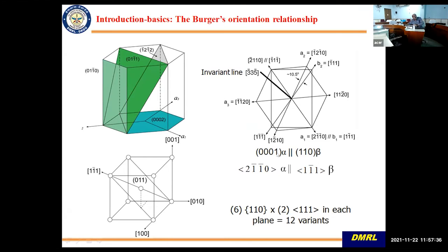So what happens is 001 of alpha, which is this basal plane, or 002 matches onto the 110 of beta, and one of the close pack directions, 1 bar 1 bar 0 of this, matches onto this direction, one of the diagonals, this or this. So there are 6 110 planes, and in each 110 plane, there are two close pack directions, 111 types. So this gives 12 variants of the alpha phase when beta is transforming to alpha.